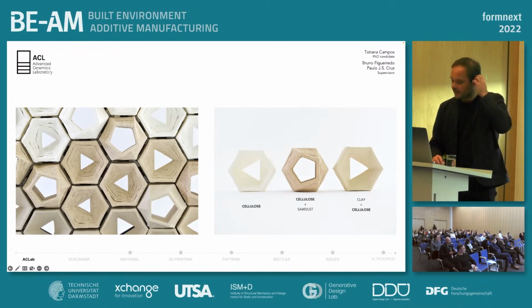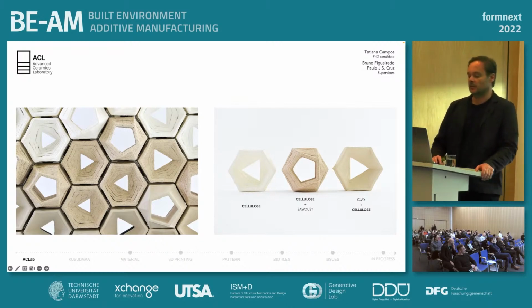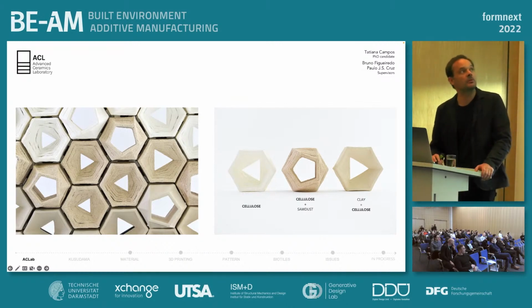Despite the lamination of the blocks made only with starch and cellulose, the test showed that the ability of 3D printing with these materials is quite achievable. By also adding a small amount of cellulose fibers to clay, we noticed that there is less deformation of these pieces when they are drying and fired, compared to pieces that we were printing only with clay.